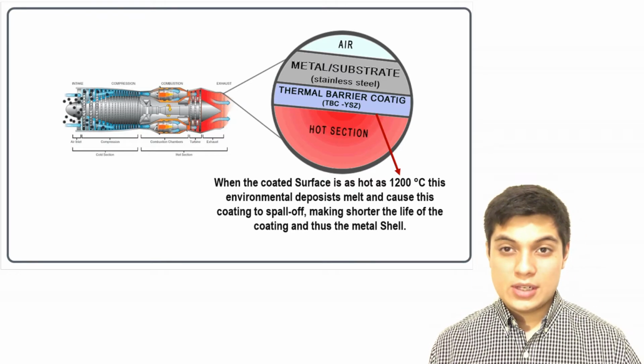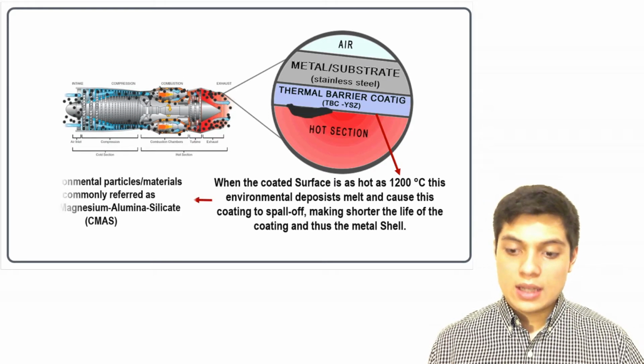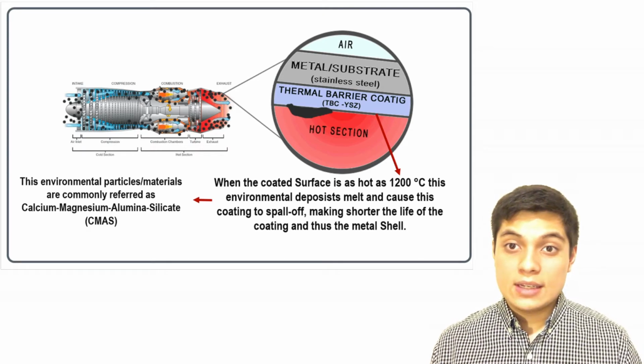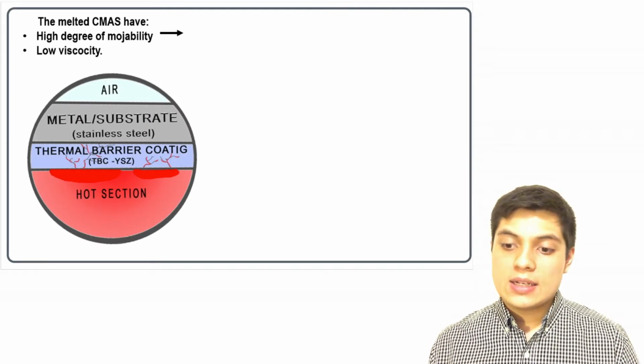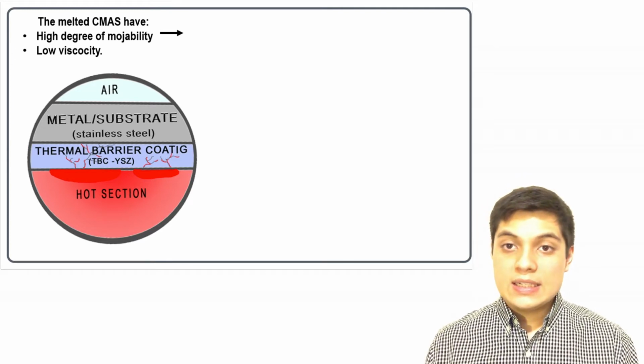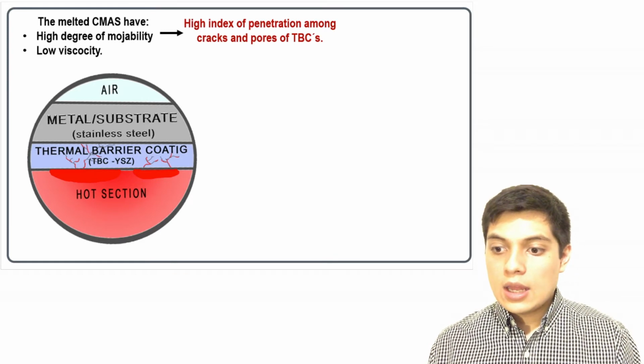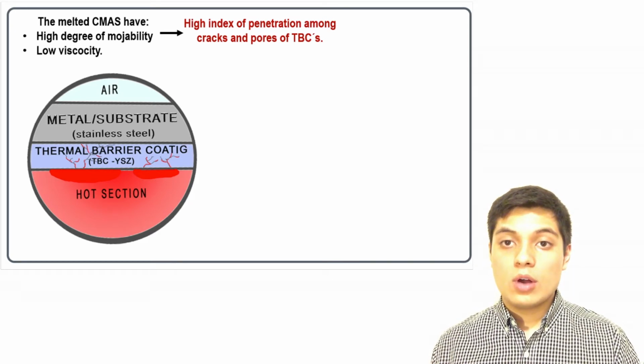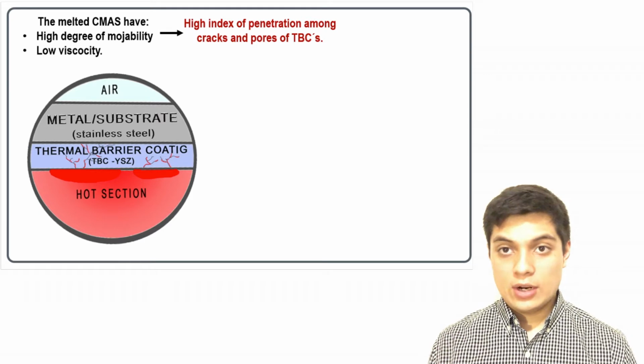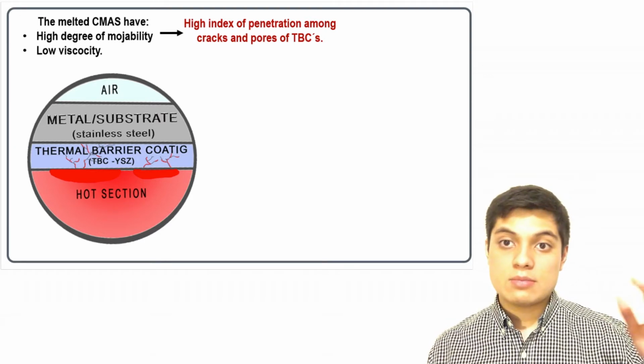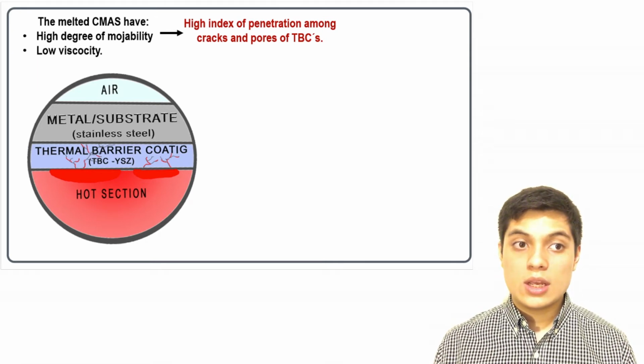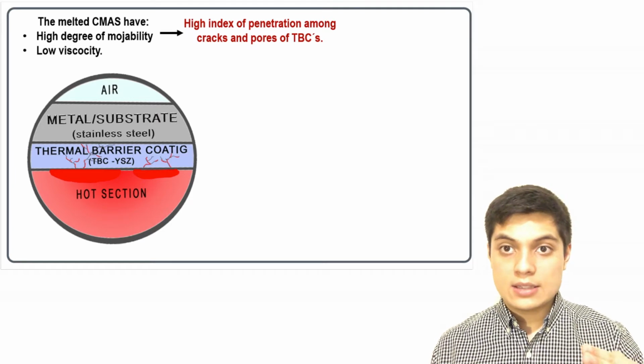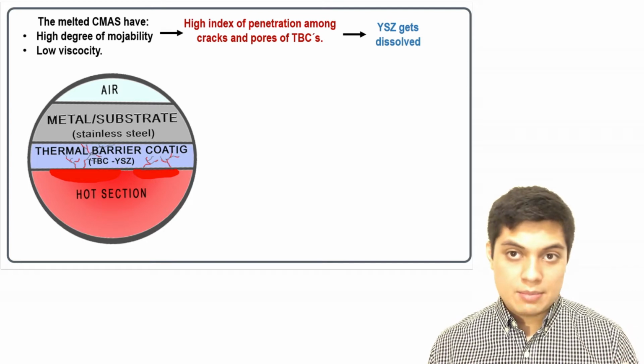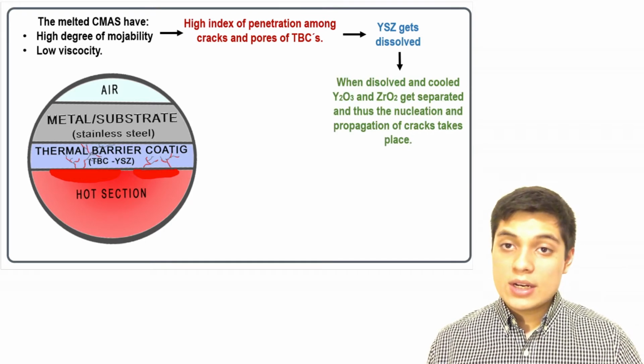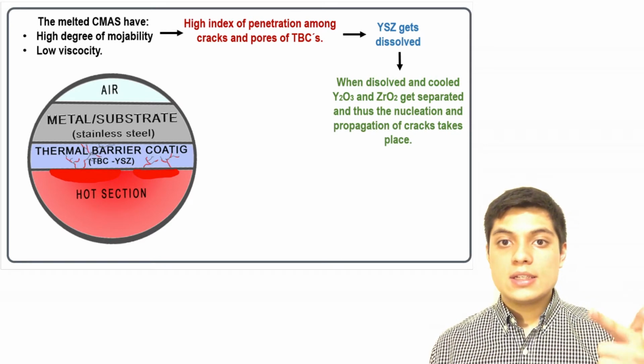These types of materials or particles are commonly referred to as calcium magnesium alumina silicate, or more commonly CMAS. The main properties of CMAS are a high degree of wettability and low viscosity, and these properties cause a high index of penetration among the cracks and pores of the thermal barrier coatings. That means if our yttria-stabilized zirconia has many cracks and many pores, it is going to be more susceptible to the propagation and entrance of these CMAS materials. When the CMAS melts, the yttria-stabilized zirconia gets dissolved, and when it gets dissolved, it separates into two phases, the yttria phase and the zirconia phase.